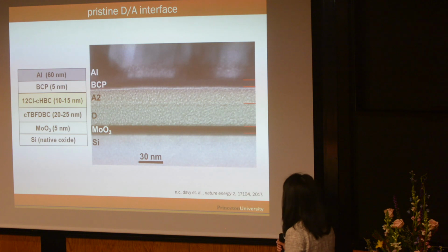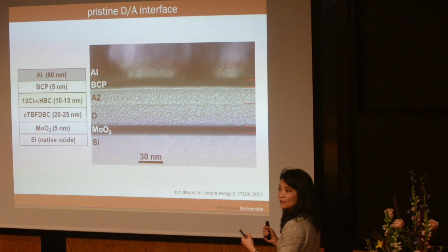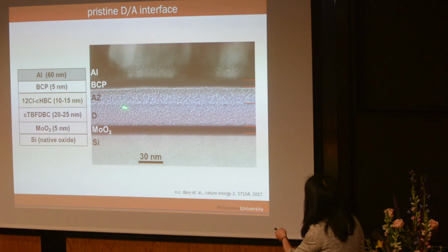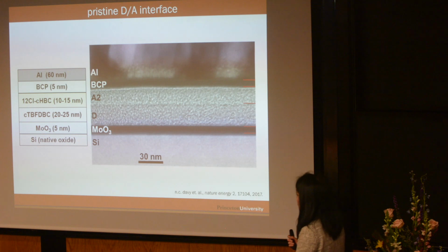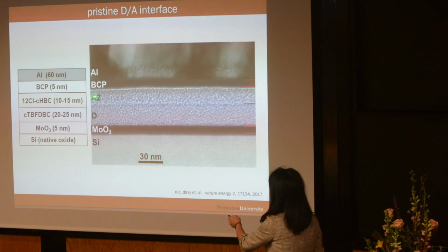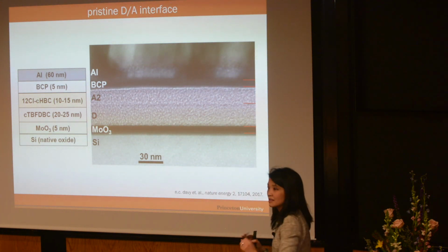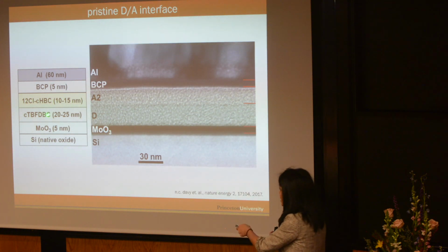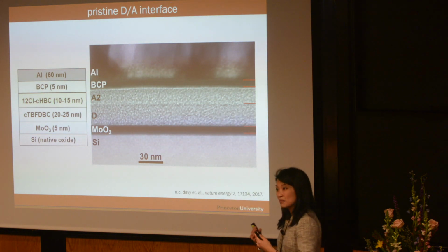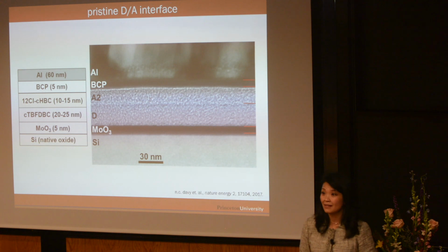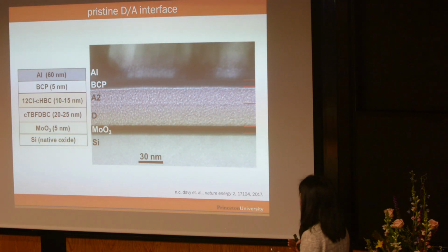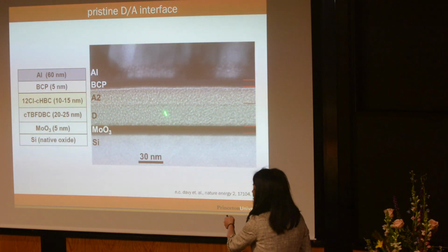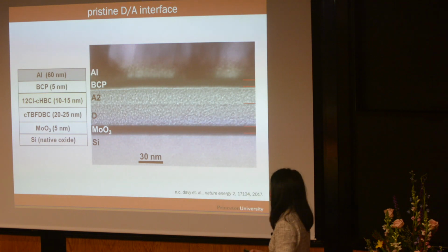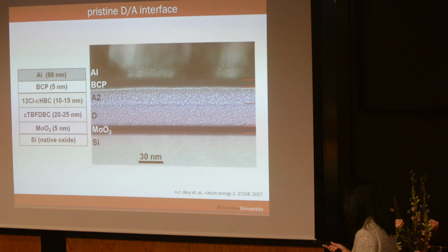This is for the skeptics out there. I wanted to show you that our films are indeed amorphous. So this is the donor-acceptor interface. And so you can see that the interface is pristine. There's no long-range order. This is cross-section of the donor or the acceptor. And again, look at the thicknesses. They're very thin. We intentionally keep these thin because they're amorphous, so charge transport is not high, right? So you're limited by charge transport. So by keeping this thin, you can effectively extract the charges at the external electrodes.